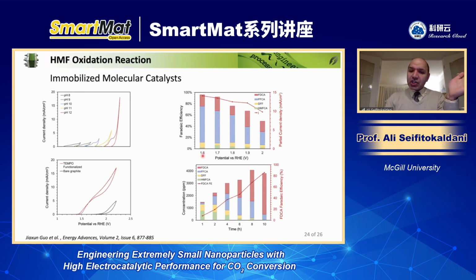To avoid that, we were utilizing pH 8, and then we were applying different potentials. The potential could start from 1.6 and go all the way to 2, but then the larger potential again promotes the oxygen evolution reaction, and that's why you don't see the HMF products efficiency, or sorry, the selectivity, add up to 100%, because the rest is just oxygen.